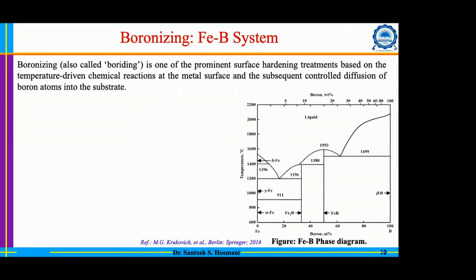Now fundamentally we need to understand the iron-boron phase diagram, and unlike the iron-carbon and iron-nitrogen phase diagrams, the iron-boron phase diagram looks entirely different. In the case of the iron-nitrogen and iron-carbon systems, you have sufficient solubility for nitrogen and carbon in austenite. But that is not the case with boron. The solubility of boron in ferrite as well as austenite is extremely poor.